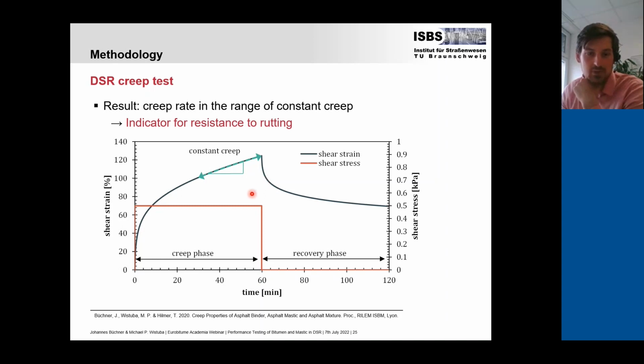And why we extended this time so much is we wanted to acquire this linear behavior, what we see here, this linear creep, this constant creep. And actually, we look at the creep rate in this range of constant creep, and this creep rate is a rheological parameter, which is an indicator for resistance to rutting in our test methodology.